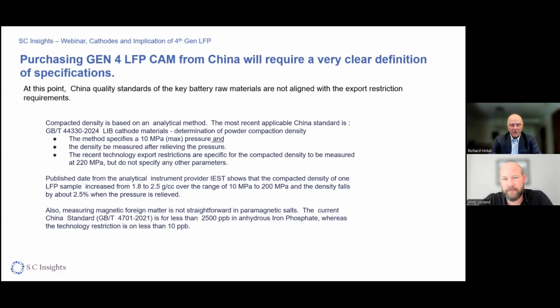Now, there are a lot of companies who provide this kind of compaction density testing equipment. I list one here, IEST, if someone wants to look it up. But there's one example given where this compaction density can go from 1.8 up to 2.5 grams per cc over the 10 to 200 megapascal range, and that you lose about 2.5% of your density when you relieve the pressure on the sample. So how do you set a specification? You're not going to be able to rely on a GB standard here. You're going to have to really dive into the details of the method as well as the specification in order to set a specification for a powder you want to buy.